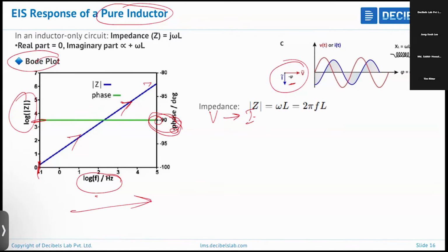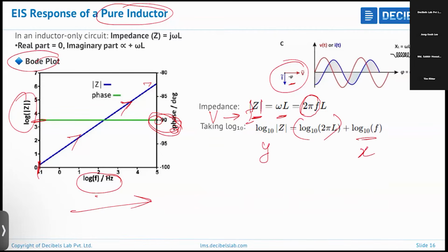So the overall impedance equation: the absolute value of impedance is equal to omega into L. We know that omega is 2 pi f, so Z is 2 pi f into L, and if you take log Z, it means log of 2 pi L plus log f, and this is actually a positive slope you get. So this is y, and this is x, and this is the intercept and slope. You can extract the inductance from this graph.